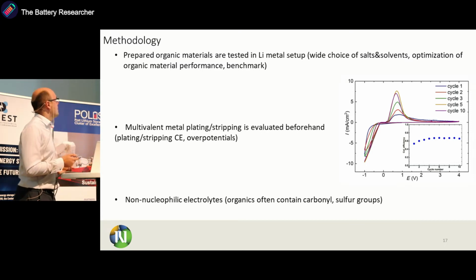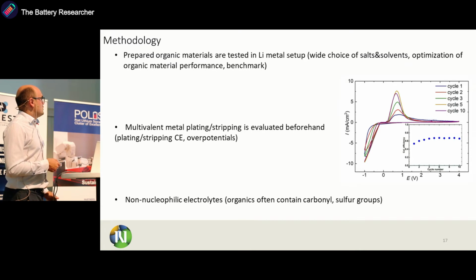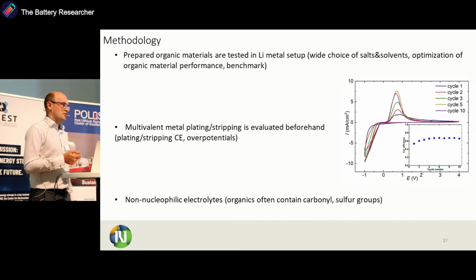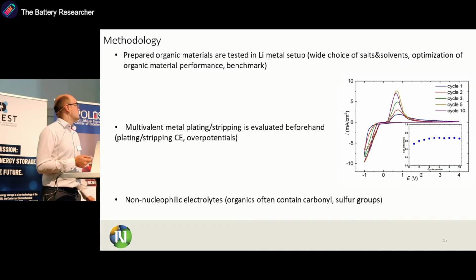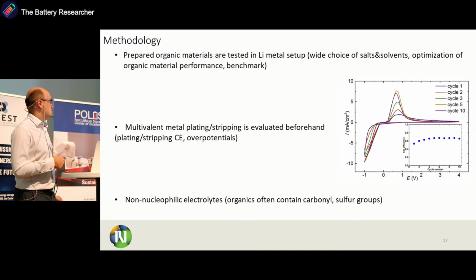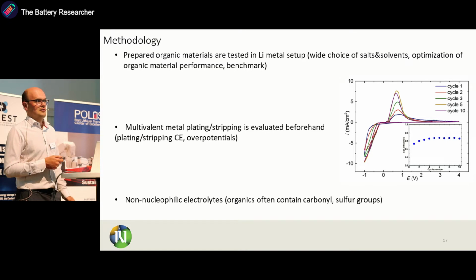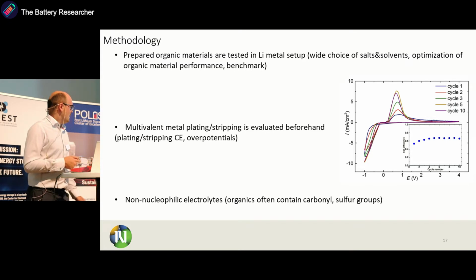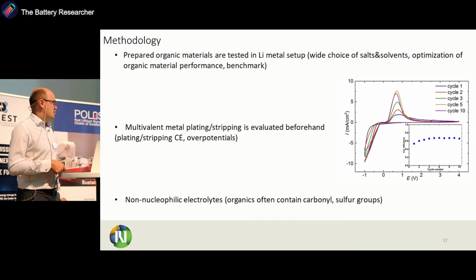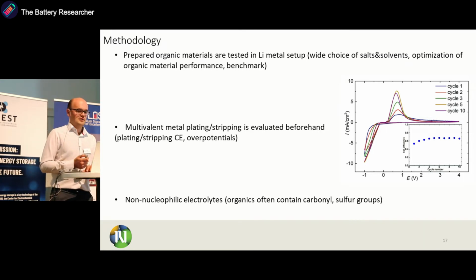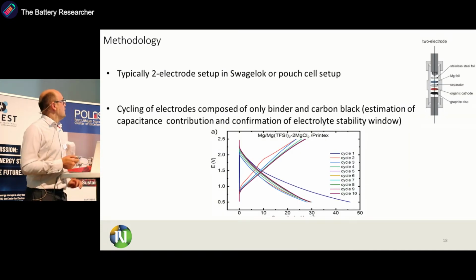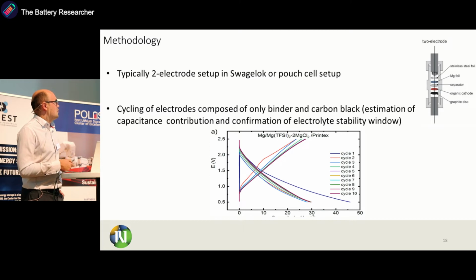phenomena ongoing. It is really important to evaluate multivalent metal plating and stripping beforehand, especially if you're doing cycling in half cells. This gives you then information about Coulombic efficiency and overpotentials that you can expect. And also because organics often contain carbonyls or sulfur groups, you need non-nucleophilic electrolytes so that you prevent side reactions. Then we typically do our testing in 2 electrode setup in either Swagelok or pouch cells.